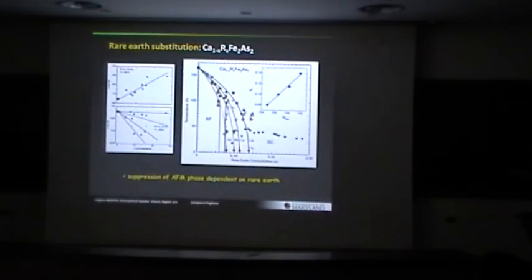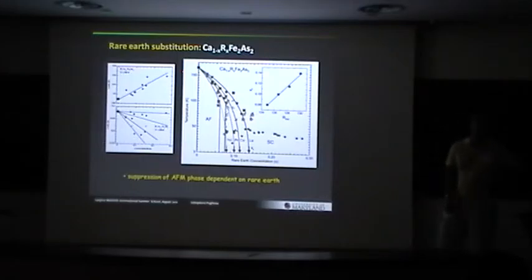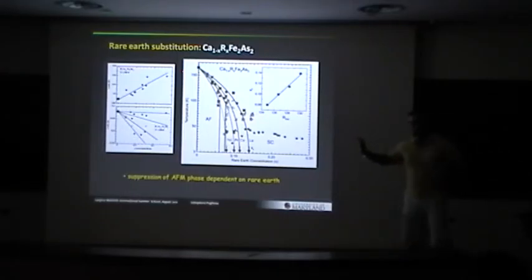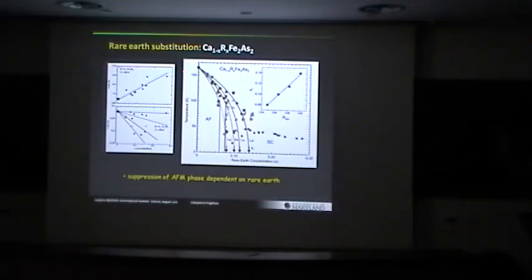I have the feeling that if I were a student watching all of these presentations, I would say this is not a field I want to go into, because I see a whole zoo of materials and they all seem to behave in different ways, and there's no one or two variables which seem to control their behavior. At least we haven't found them yet. What's your perspective on this? Is it just everything in details, or is there something universal that we're going to be able to extract? Well, that's why I tried to emphasize the phase diagrams. I think this is an important clue. Even here you have all this weird behavior. But at the end of the day, here's an example: you have a phase diagram where you're suppressing magnetism and you're getting superconductivity. Very bluntly, I think that's common to almost all these materials, except maybe the iron selenide.